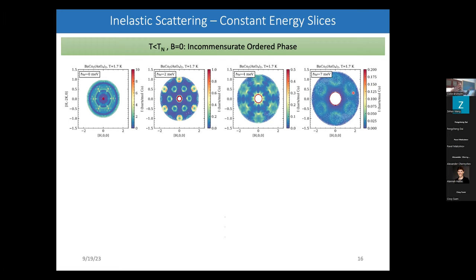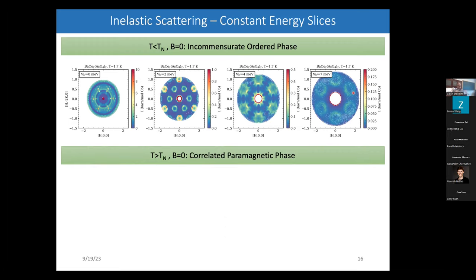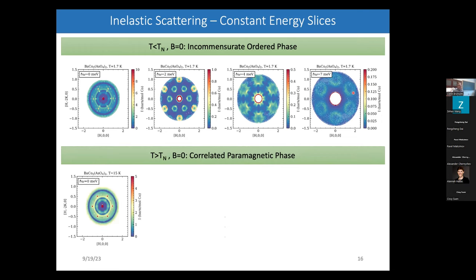So this is what happens when I go to higher and higher energy transfer. I lose the signatures of the competing interactions, and I notice it kind of reveals itself as essentially being an easy plane ferromagnet. And you see similar things if you go to temperatures above the ordering temperature.